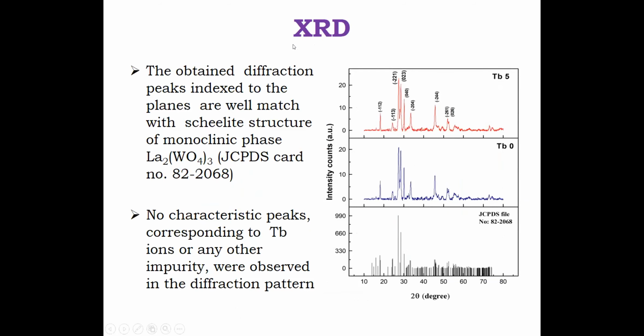The XRD pattern of the pristine as well as terbium doped sample is shown here. The standard pattern is also given for comparison. The observed peak positions of the pure sample TB0 were well matched with the standard pattern, JCPDS card number 82-2068, and it has a scheelite monoclinic phase with the C2/c space group. The diffraction pattern of the doped sample was also well matched with the monoclinic phase. No additional peaks corresponding to terbium or any other impurities were observed.